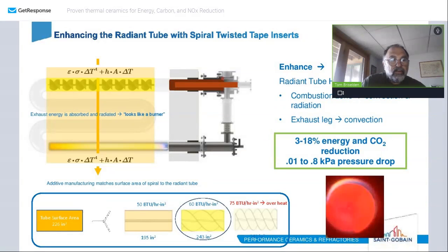The use of spiral twisted tape inserts provides an effective means, when combined with additive manufacturing, to make a device that absorbs exhaust energy and re-radiates similar to the flame. Interestingly, we find that a ratio of the surface area of the tube to that of the twisted tape being approximately 1 gives the ideal balance of radiation and convection in the exhaust leg.